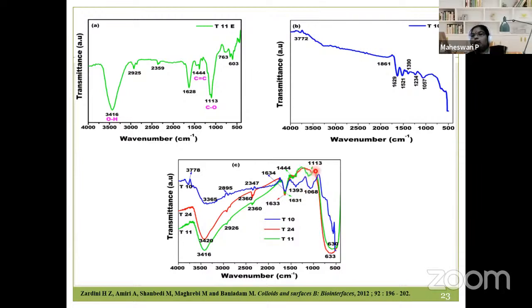There is a peak over here, and also the peak is becoming like this here, which indicates the compound has really interacted with TiO2. And also you can see a drastic change here. And also around 1634, you can see there is a shifting, and there is a broader peak around 1393 and 1068. Which means the amide and the amine groups of the protein powder have reacted with TiO2.